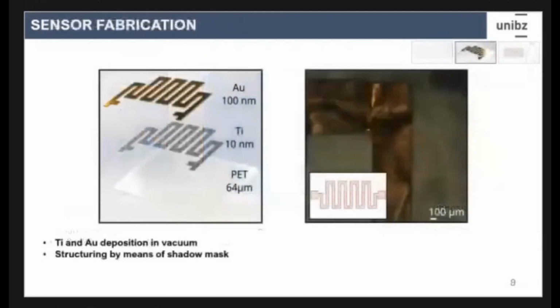After that, we created the temperature sensor by following conventional thin-film processing techniques. In this case, we put the substrate under vacuum and structured the temperature sensor using a shadow mask. So we took the film, put it on a surface, put a shadow mask on it, and pressed it. It helped a lot because it evens the surface even more. And we deposited by means of E-beam in vacuum 10 nanometers of titanium, and by thermal evaporation 100 nanometers of gold. Titanium was an adhesive layer to deposit the gold on top.